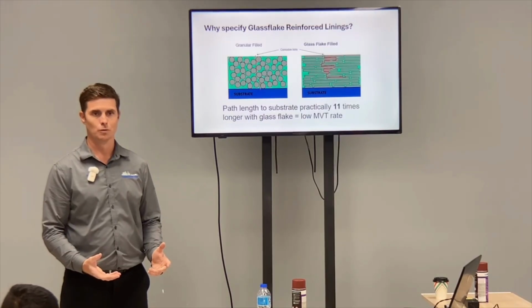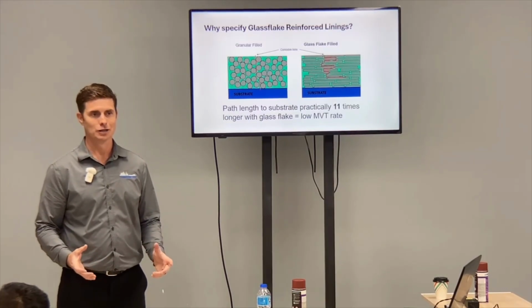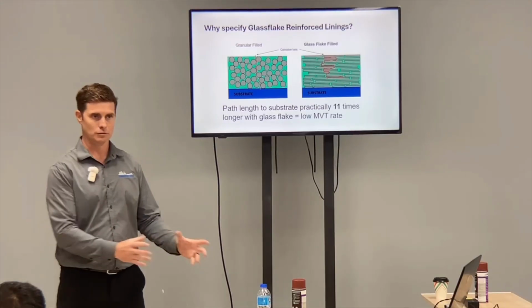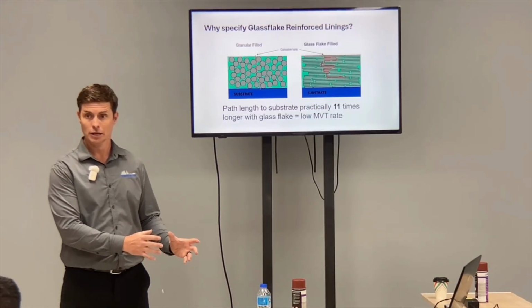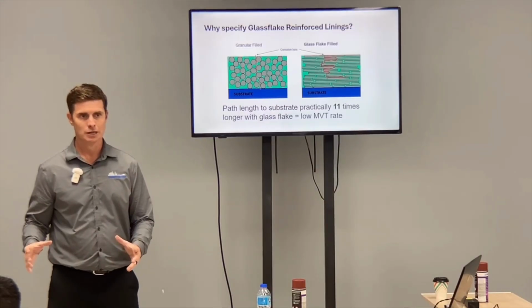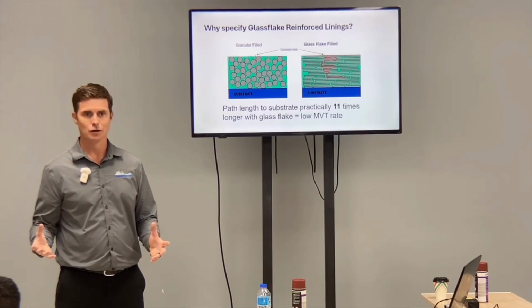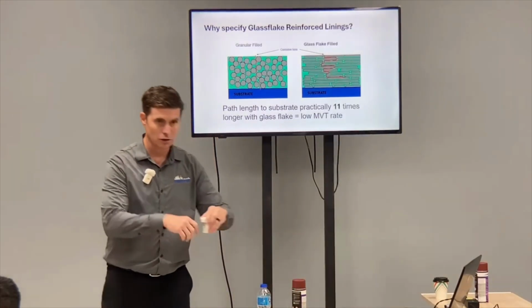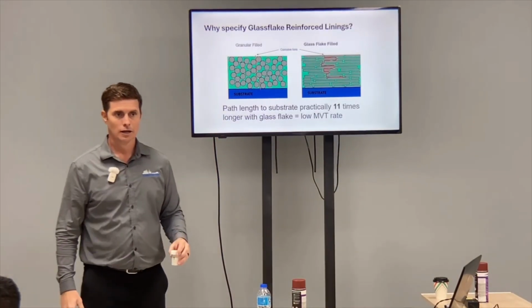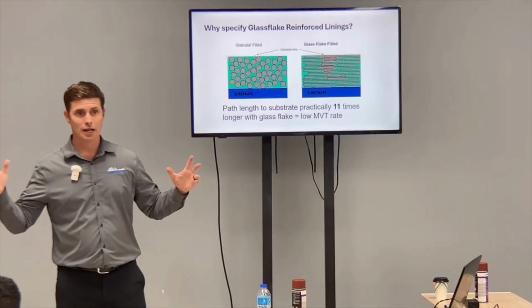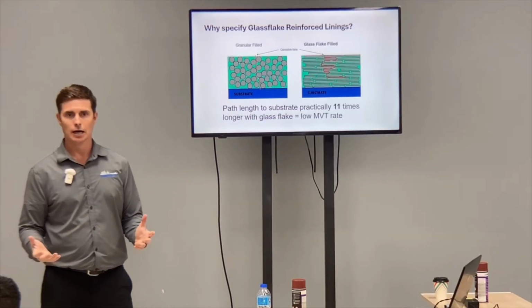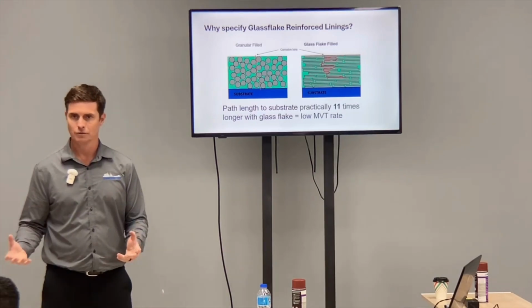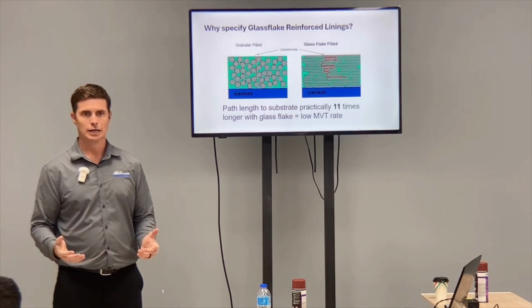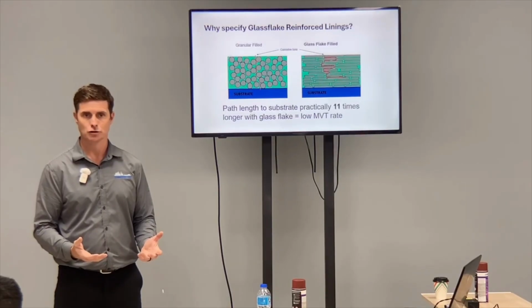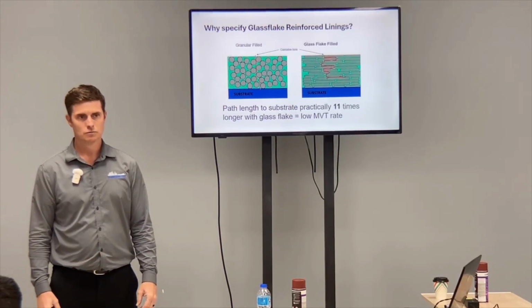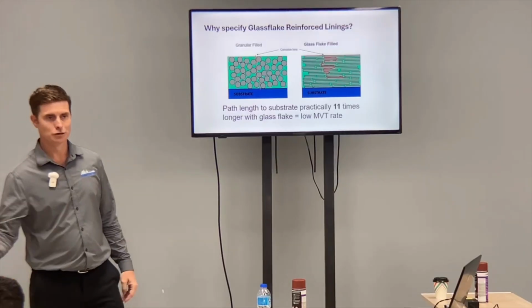You see, there's no ISO standard for glass flake coatings that says that it must have a certain performance value. I wish it did. We should look at performance-based properties. So there's a lot of coatings out there that say they're glass flake, but they can take just a little glass flake and do one of these in there and call it a glass flake coating. And it may or may not have the same performance value as a well-engineered glass flake coating with high aspect ratio thin glass flakes. Make sense? Yeah, I kind of breezed over that earlier. Thanks, Deepak.